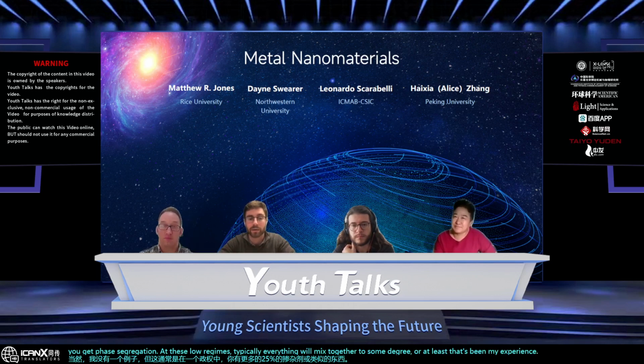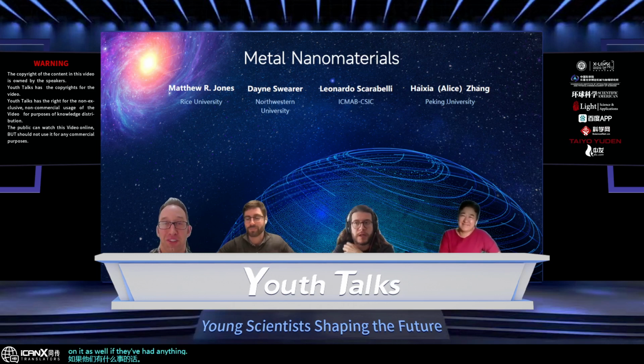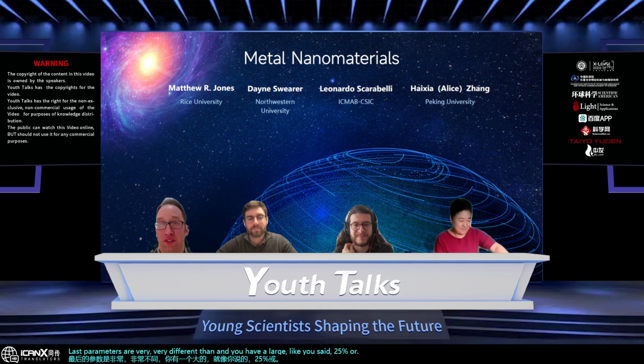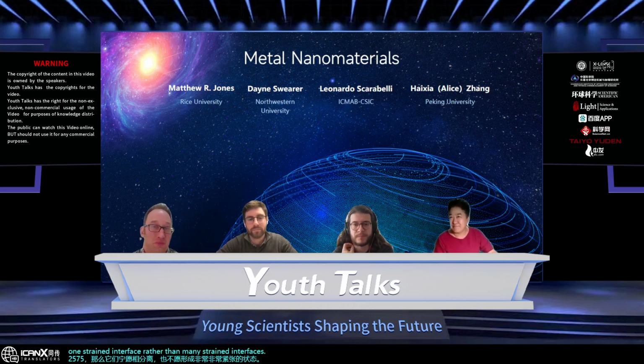Maybe Leo and Matt can comment on it as well if they've had anything pop out in their careers that's been different than that. I think you've got it. If the lattice parameters are very, very different and you have a large fraction, like you said, 25% or more, 25, 75, then they would rather phase separate than form one strained interface rather than many strained interfaces. But you're right, most of the coinage metals are almost 100% miscible with each other. So that's not too hard to make alloys.